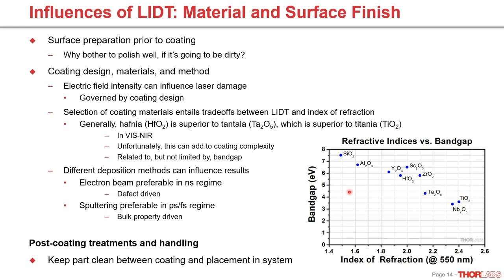So hafnia is a good material to use. Typically it's better than tantala or titania or niobia. And again, this is in the visible. In the infrared, or in some of the other wavelength regimes, you may want to look at other materials. But unfortunately, as you can see, we have a rough trend of lower band gap with higher index. And as any coating designer can tell you, you want to have a large contrast between your high and your low index layers.